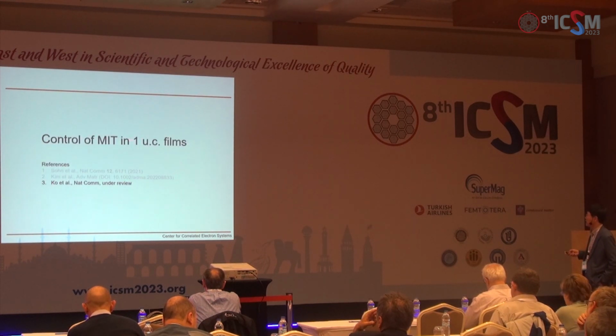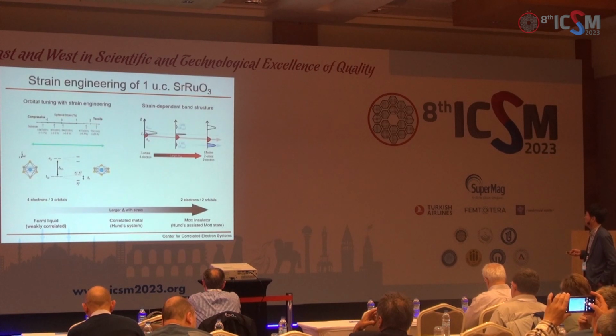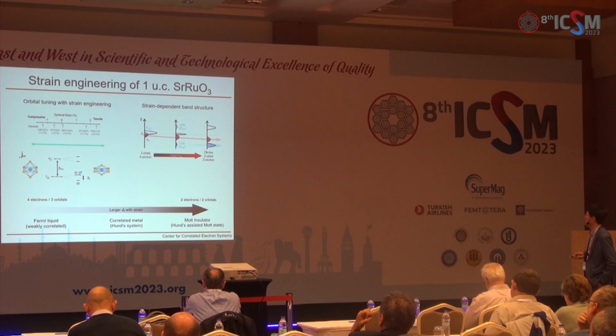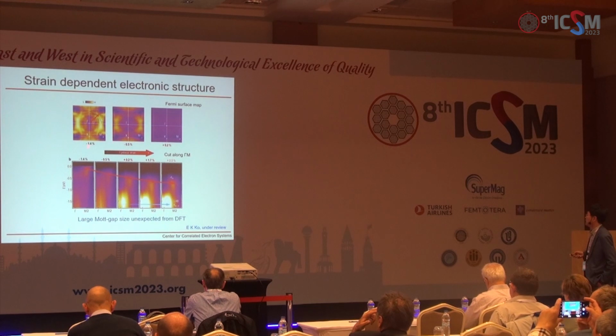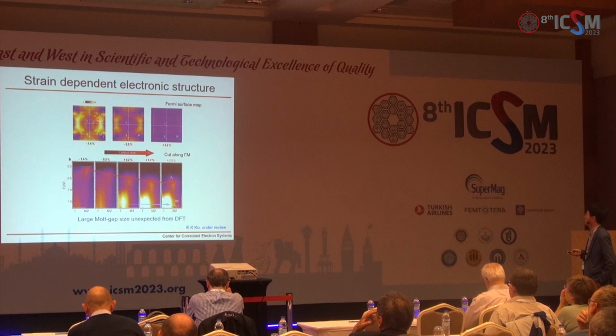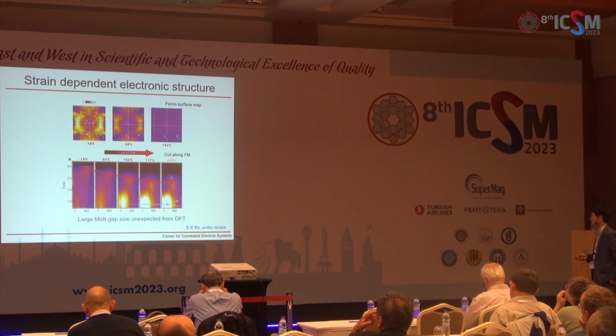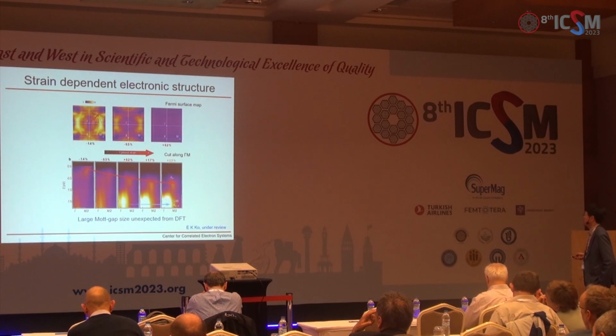We can also control the metal insulator transition using strain, which changes the shape of the octahedron. And indeed, we did that. Here, with the compressive strain, we have a fairly good metal, a coherent metal. With the tensile strain, we have a Mott insulating state here.